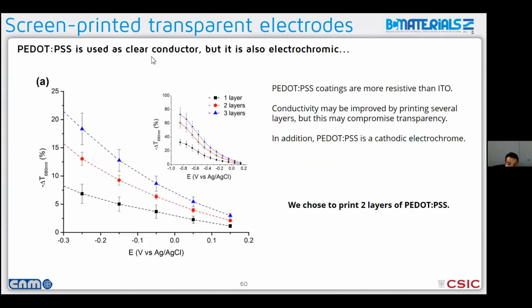PEDOT:PSS is nice as a transparent electrode, but the problem is that it's also electrochromic. So we needed to be careful because we have to have a material that is a good conductor, but at the same time, it also needs to be transparent, and it mustn't mask the color change of our main electrochromic. So we studied the effect of printing 1, 2, or 3 layers of PEDOT:PSS. The nice thing is that these layers are extremely thin. They were surprisingly thin. So one layer of PEDOT:PSS is maybe half a micron or less. So you can print 2 layers and it's still 1 micron, and 3 layers a micron and a half.